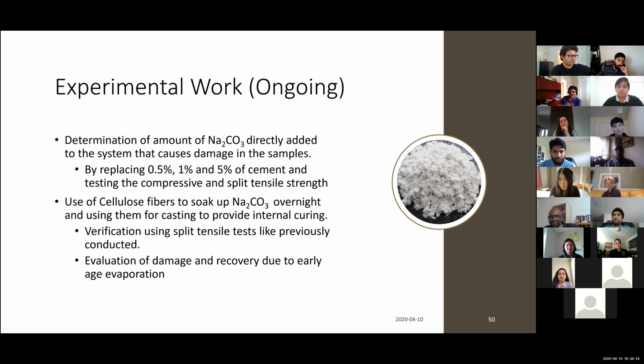I was a little bit surprised by the fact that you said you need 90% stress to create damage in compression. I really find that quite surprising, because if you look at previous permeability work, I think you are introducing some post-structural damage at 30%. As you know, the typical curves are... Nemi, so that was not to introduce damage in permeability, that was to introduce damage in compression. I know that. In terms of permeability, that's not the case. I know that, but I think the damage is damage for me.